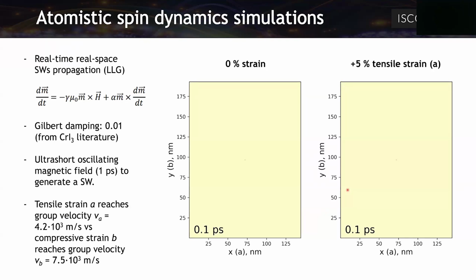Then once we have this, we can also go to real space and real time, and we can study how this spin wave propagation works. For that, we use the Landau-Lifshitz-Gilbert equation that describes the precession of the spins, and we have a damping term that makes the spin wave end at the end, so it's relaxing. For that, we use Gilbert damping from the literature. In this case, we use the one of chromium triiodide. So this is a phenomenological approach, but taken from a related material. Now we are working on implementing ab initio calculations to determine this for each material.